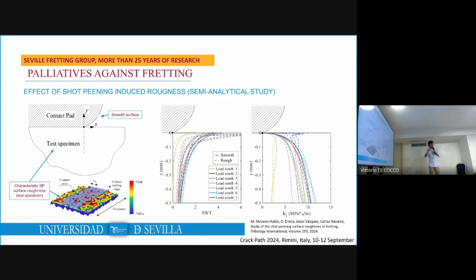In order to analyze these results, we did some numerical models. In this case, with this finite element model, we introduced the characteristic shot peening surface condition in the model. And we analyzed what happened on the surface and below the surface. Here we can observe the Smith-Watson-Topper distribution and also the stress intensity factor mode 1 along a line starting from the most damaging point of the contact surface, the hot spot, and perpendicular to the contact surface. We can observe the following.